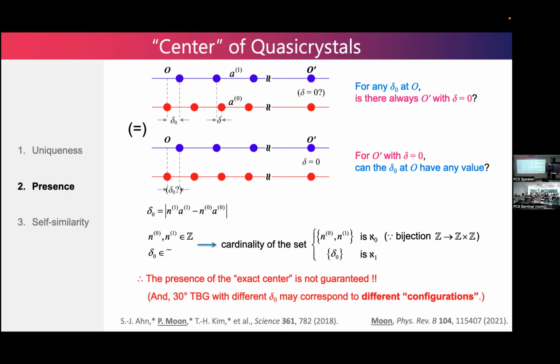So if you make two graphene quasicrystals, their microstructures might be different. But unfortunately, this will not affect the band structure and physical properties, or almost not visibly. If we go to a very infinite quasicrystal, then does delta become dense? Am I right? I mean the appearance of delta, the probability distribution would be continuous. It is completely even, I mean flat, and it is dense.